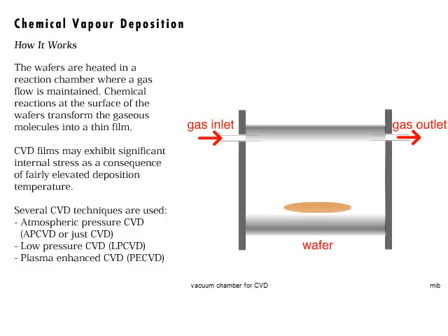The most frequent layers used in micromachining are polysilicon films deposited at 600 degrees C by LP-CVD from silane gas. Low-stress silicon dioxide deposited, for example, by PE-CVD from silane and oxygen between 300 and 500 degrees C. Silicon nitride deposited at 800 degrees by LP-CVD from dichlorosilane and ammonia.